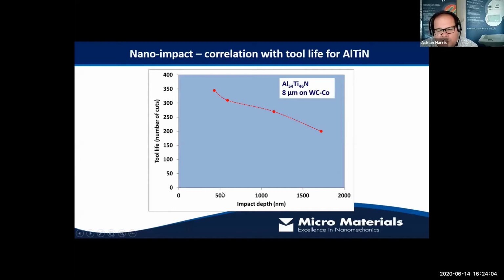It's kind of logical, right? There's been less damage in this sample, with smaller impact depth and a better tool life. And at the other end of the scale, a much bigger impact depth, over 3 times deeper, and something a little over half of the tool life. So what's different about these four coatings? They are essentially the same material, but their structure is different.